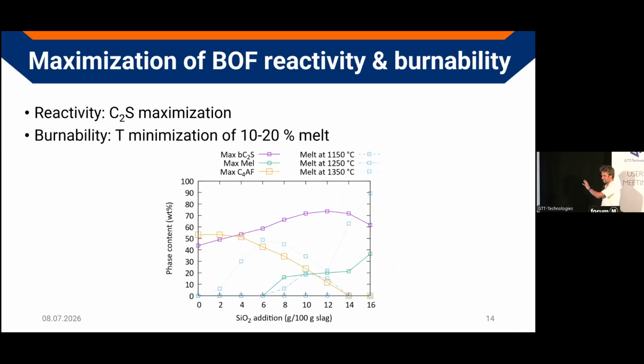And why I also wanted to show this is that it's not always as straightforward as adding calcium carbonate to increase your carbonation reactivity. If we work with BOF slags, you actually have to go the other way, because your reactivity or your strength after carbonation comes from calcium silicates, and then the decalcium silicates, and not from free lime as you would have in a BOF slag. We actually have to add some silica to increase the dicalcium silicate content. Yeah, so we have this maximum calcium silicate content between 10 and 14 gram of silica addition.